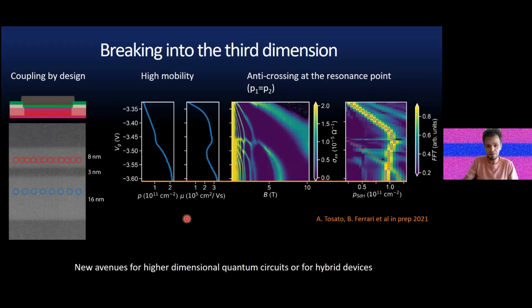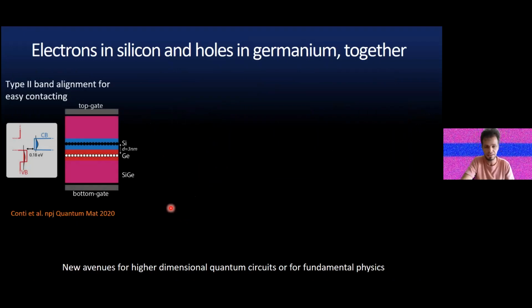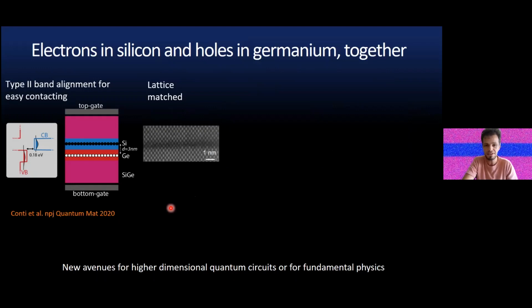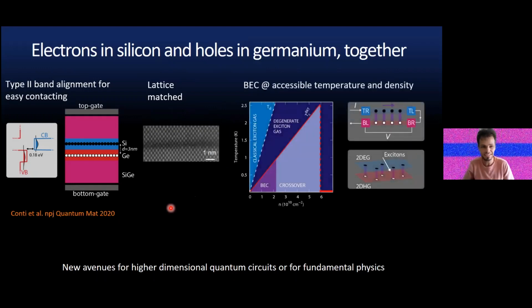And if you're looking further down the track, the last result I really want to put forward is more of a theoretical paper. It's actually my first theoretical-only paper I have co-authored. So I came up with this heterostructure where we try to combine electrons in silicon and holes in germanium, so let's say the best of the two platforms together. And why? Because we can really have a very interesting band structure here, because there's a type 2 band alignment. This is very different from what you get with typical gallium arsenide, the III-V bilayers. So you can really position these two quantum wells very close and contact them independently, because the implants that contact the electrons will not contact electrons here, and vice versa.